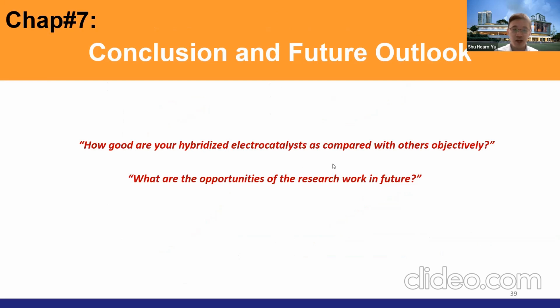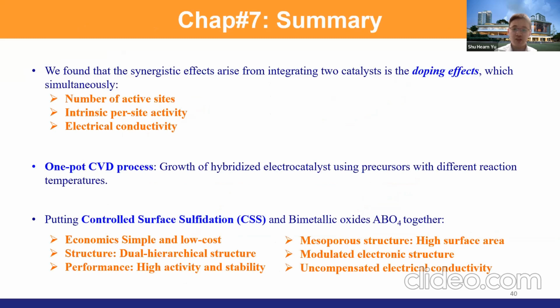And then, okay, this is almost coming to the end. So I would like to summarize what I did. I find that the synergistic effect arises from the doping effect. The doping effect can increase the number of active sites. It can also increase the intrinsic activity of the sample. It also increases the electrical conductivity.